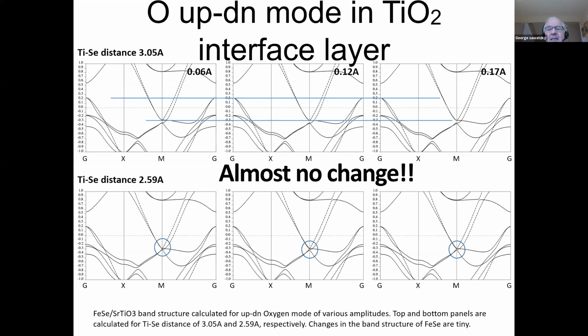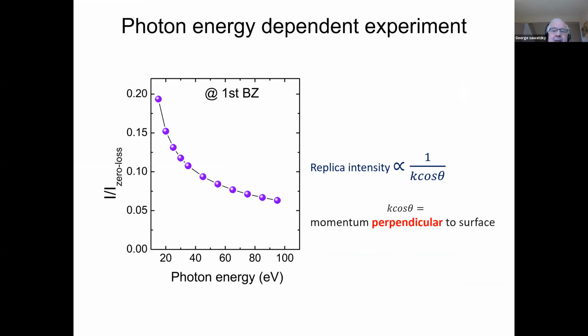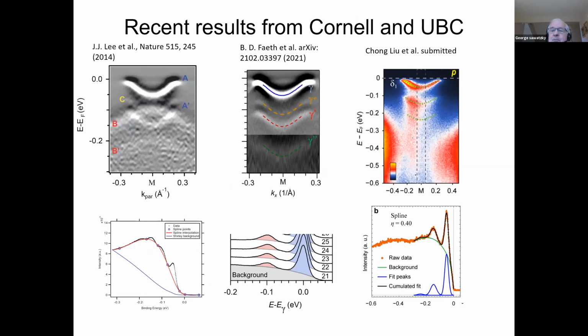So the iron d electrons really seem to be insensitive to what is happening so far away in the strontium titanate. Now, in our paper that we published about the extrinsic energy loss, we also gave the smoking gun experiment as to how to determine what it was. And that's the photon energy dependence of the replica intensity. It should go like this if it's extrinsic. And many people have tried to measure this. It's very hard to do simply because of the very large background.